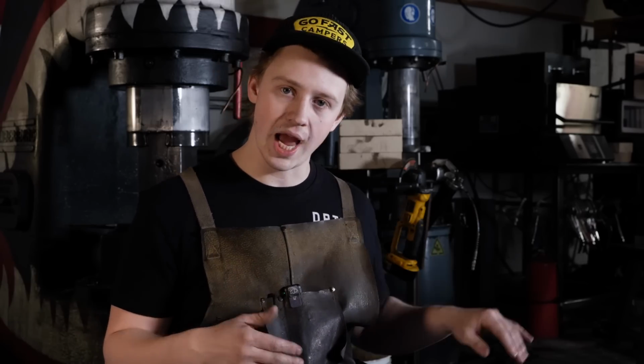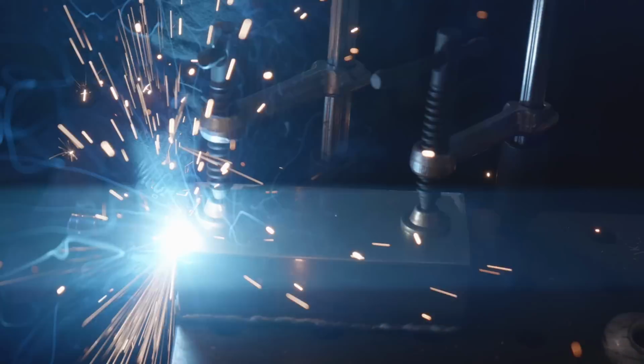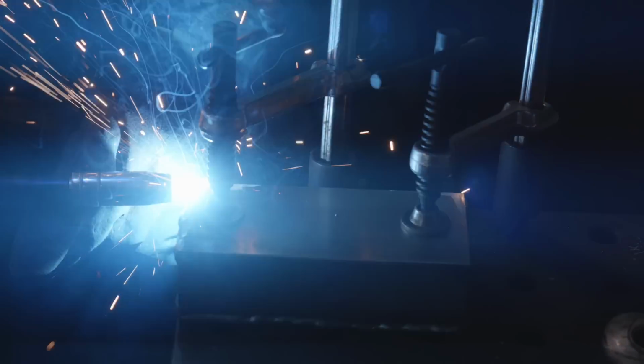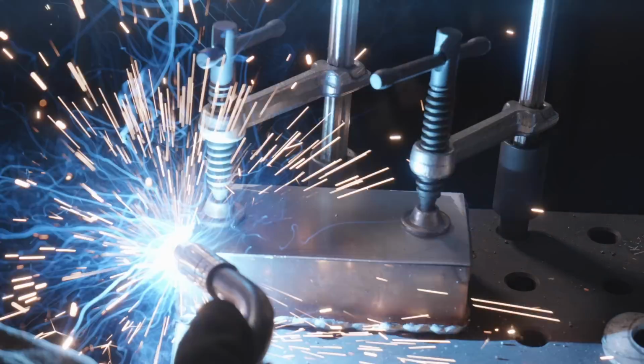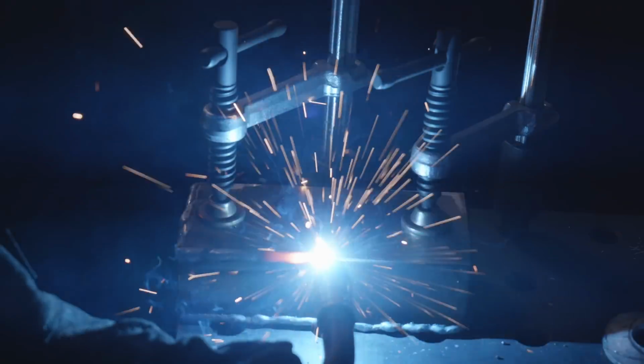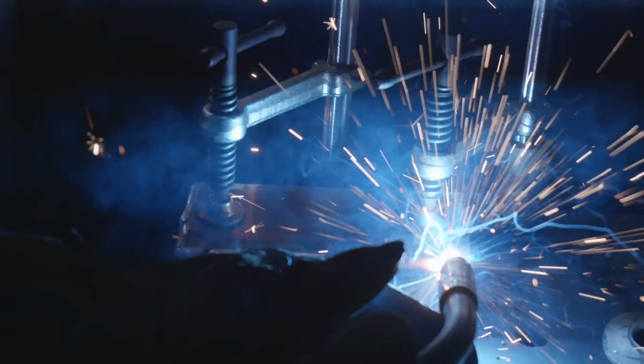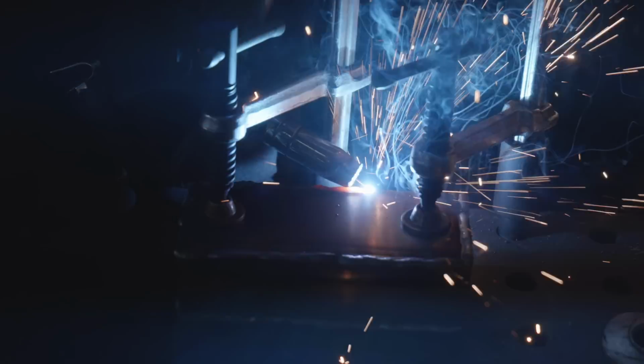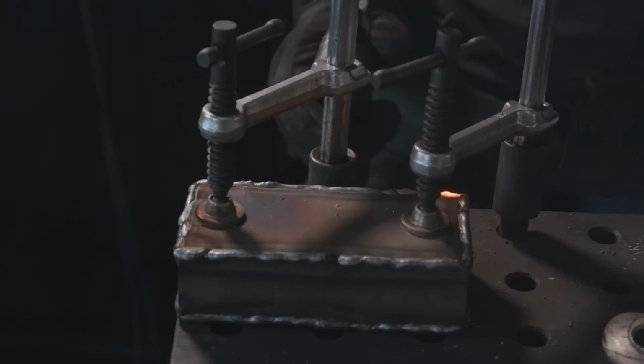The most intense way to do it, this is a process that was developed a long time ago by guys like Steve Schwarzer and Daryl Meier, was to weld a can all the way around the billet. So you're putting sheet metal on the sides of your 25 layers, and then they'll actually weld a tube into that with a little weep hole on the far side and run argon through it. So argon is an inert gas. It means that that steel is not going to oxidize, and you can get perfect forge welds. There's no oxygen coming in from anywhere, just argon running through it. So you get perfect forge welds that way. That is the most controlled way, the most consistent way to do it.